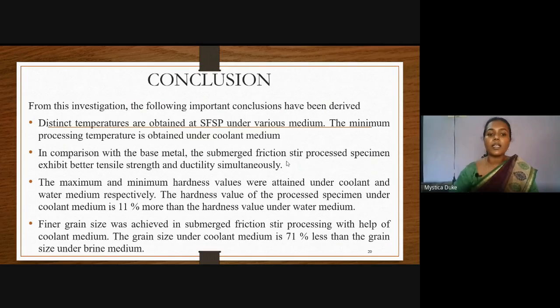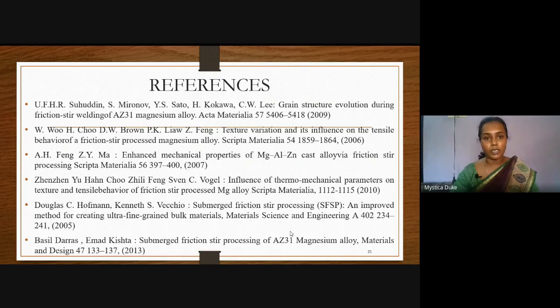And we saw that this medium, especially the cooling oil, had the tendency to maintain better tensile strength and ductility simultaneously, which is actually very hard to achieve. This was achieved by using cooling oil. Then the hardness value was also higher by using cooling oil. The hardness obtained was about 11% more than the hardness obtained under water medium. And the grain size was also smaller for the cooling medium, reduced to about 71% less than the grain size using brine medium. So these are the conclusions from our study, and these are a few of the references we have used for our study.